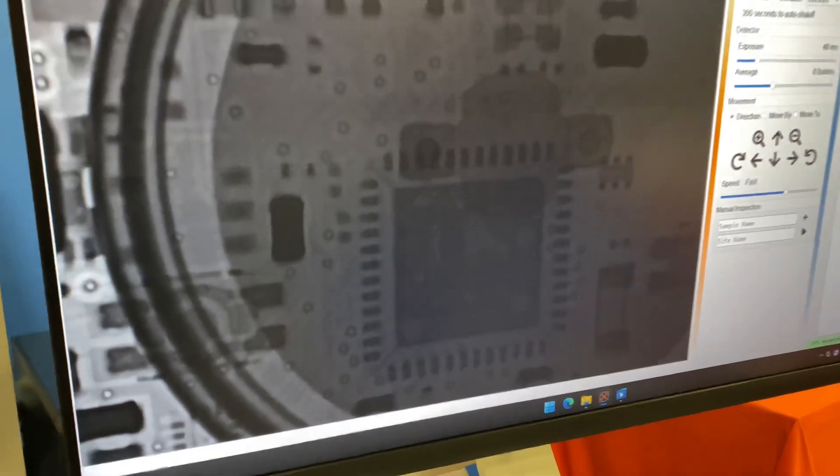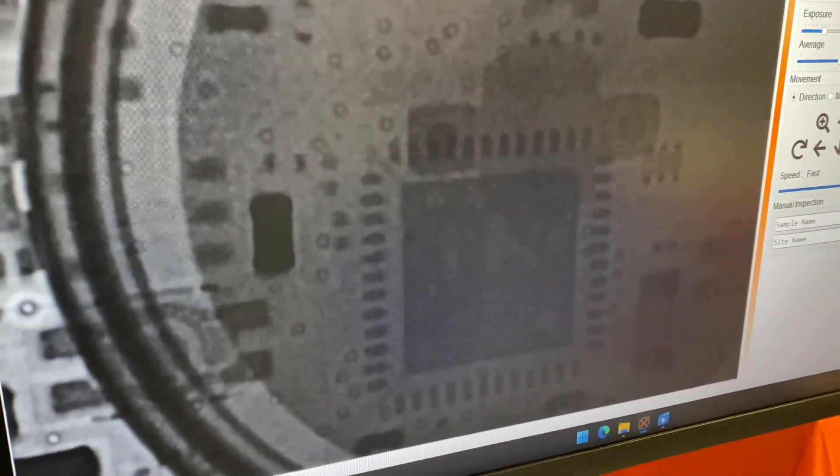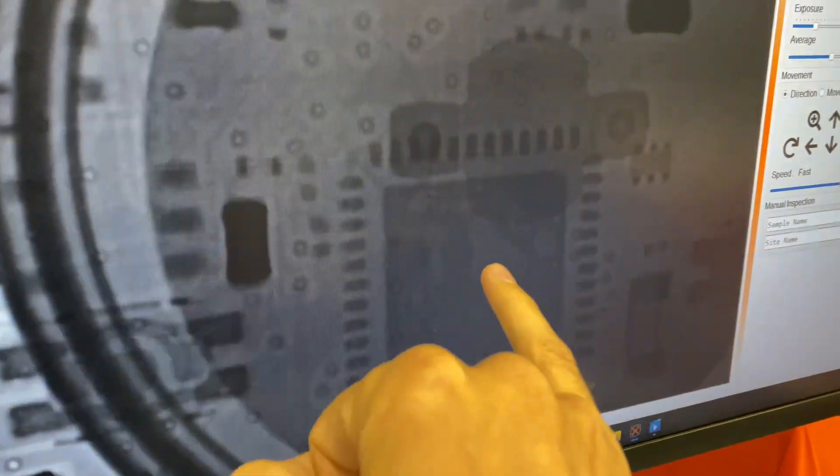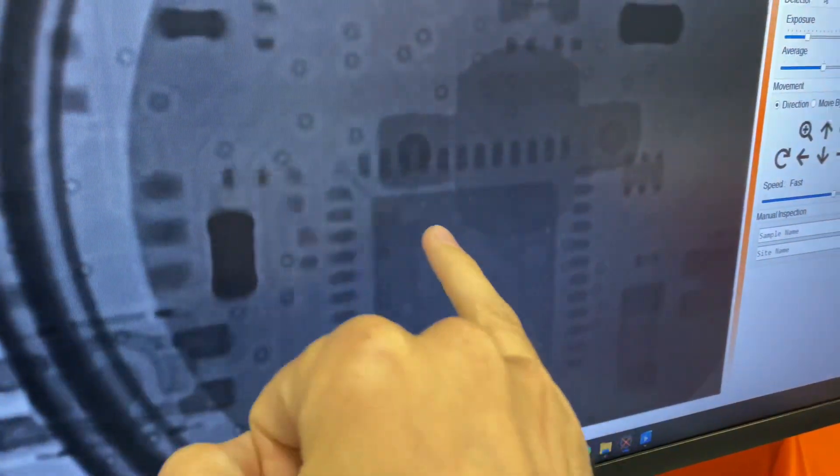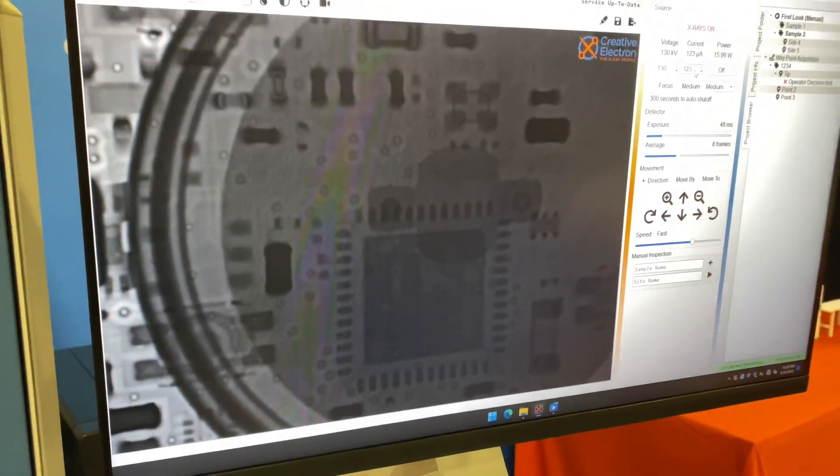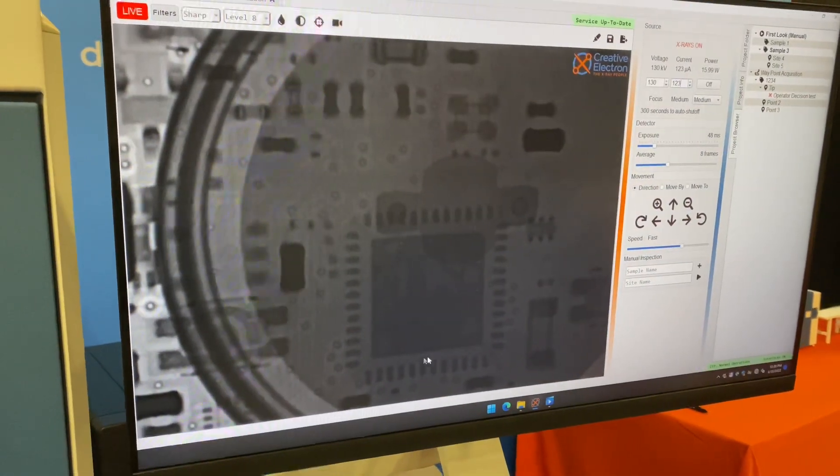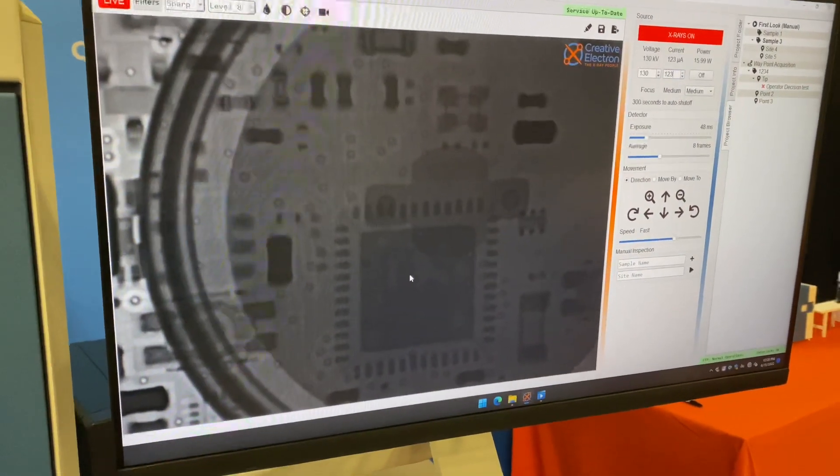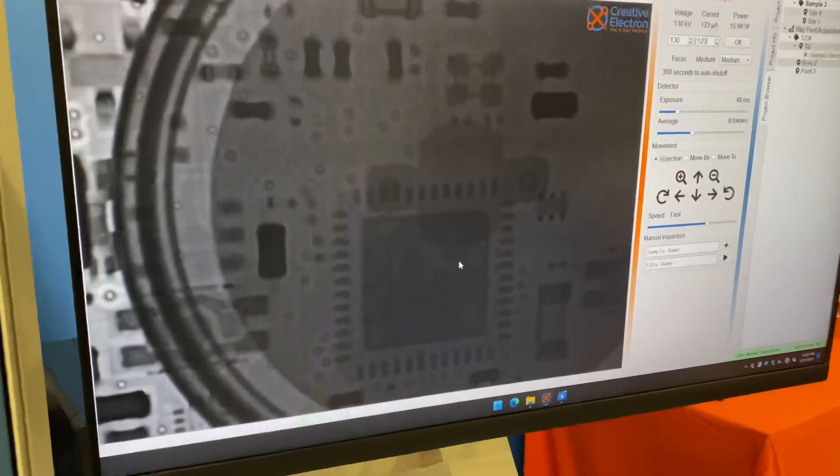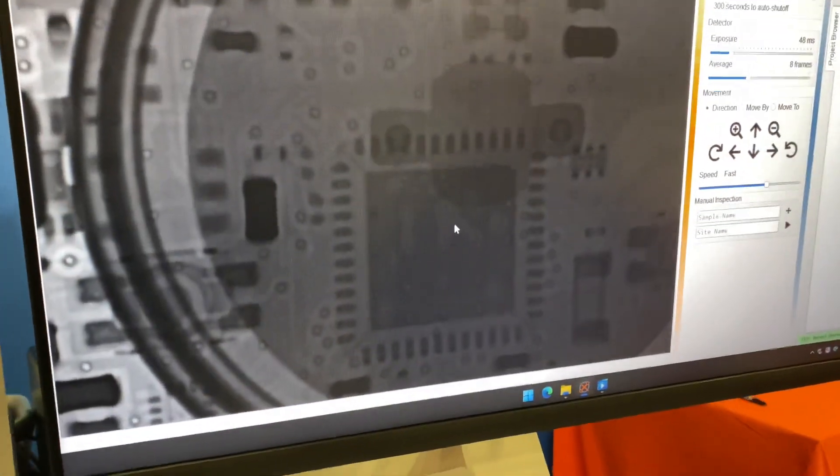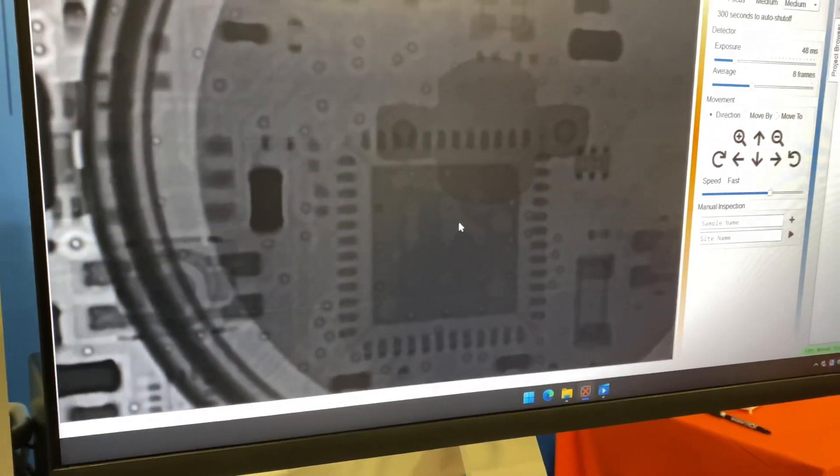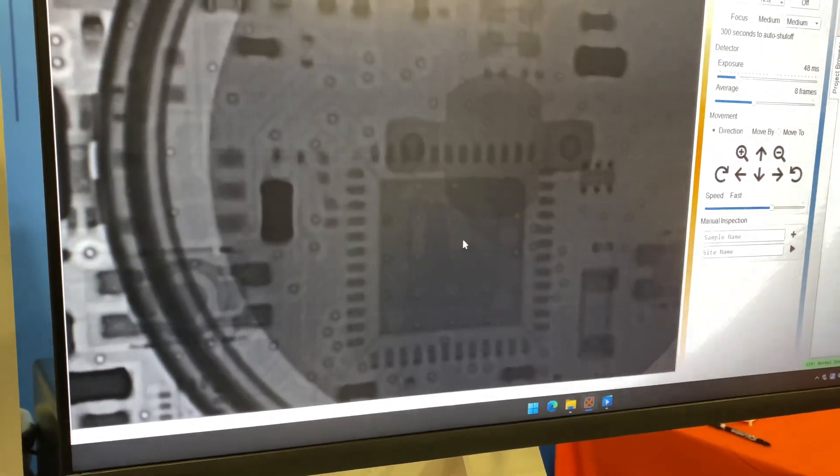Let's see if I can brighten it up just a little bit. So the voiding is this area right there that I'm seeing. Yes, that's correct. And what does that mean? That means there's air pockets in there. So this should be soldered 100% as a heat sink. So those voids can actually lead to thermal issues.